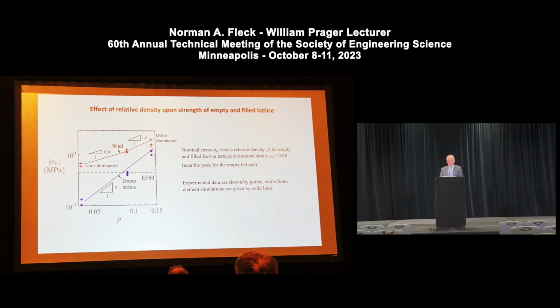I've already mentioned that the EF80 itself contributes to the stiffness, or equivalent to the strength of the EF80 matrix, not just from its incompressibility, but the fact it's got finite strength. So if we plot at a strain value of 8%, the strength of the rubber core is here. And if we compare that with the strength of an empty lattice, that's the blue line down here.